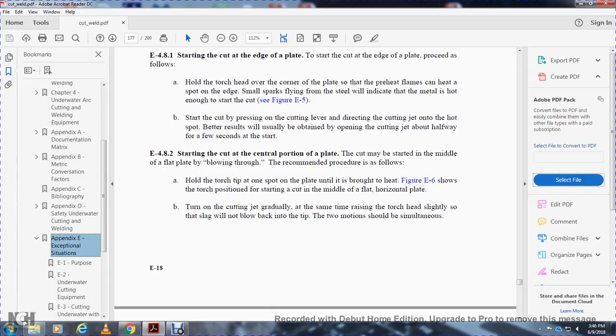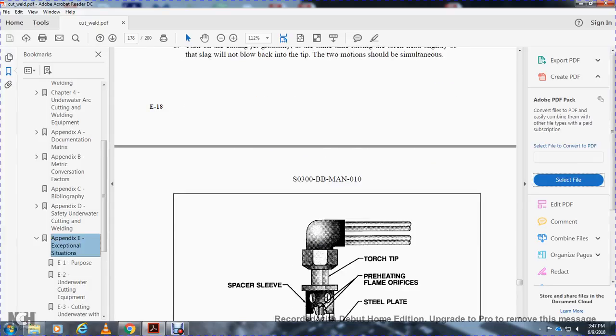E-4.8.2, starting the cut on the central portion of the plate. A cut may be started in the middle of a flat plate by blowing through, using the recommended procedure. Hold the torch at one spot on the plate until the plate is brought to heat. Figure E6 shows the torch position for starting a cut in the middle of a flat horizontal plate. Turn on the cutting jet gradually, at the same time raising the torch head slightly so the slag will not blow back onto the tip. The two motions should be done simultaneously.